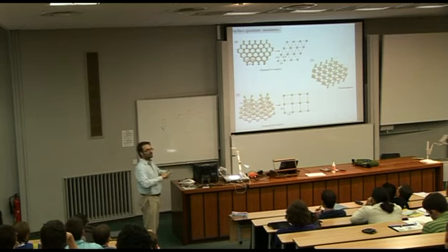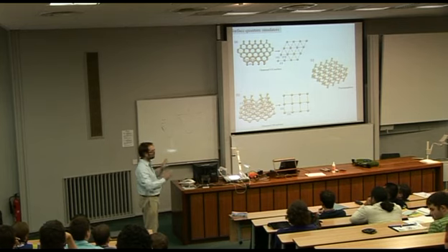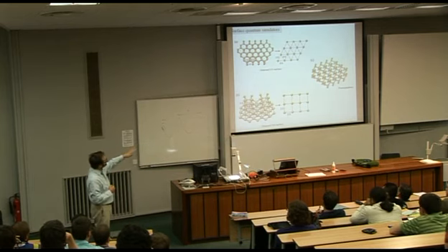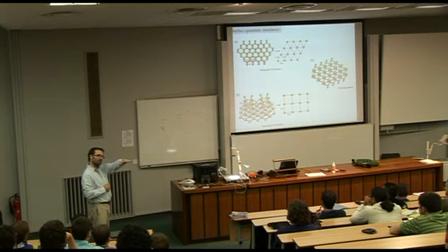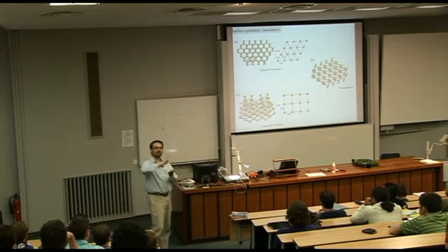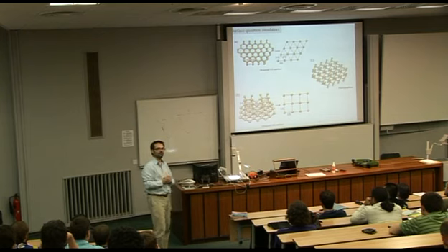Then you fluorinate the surface, using HF acid, and in the end you get a diamond surface where each carbon atom binds exactly to one fluorine. And now the diamond has different surfaces depending on the cuts that you're making.